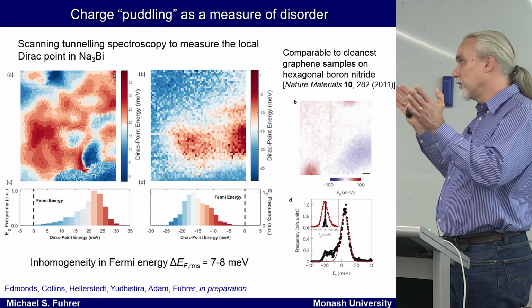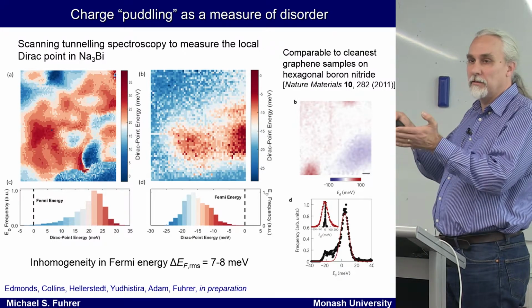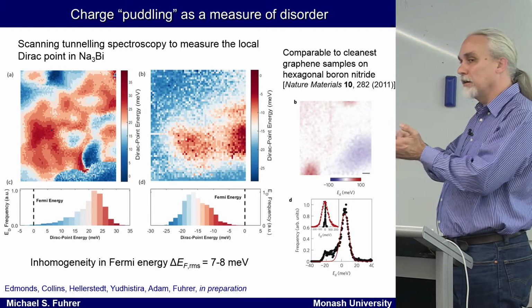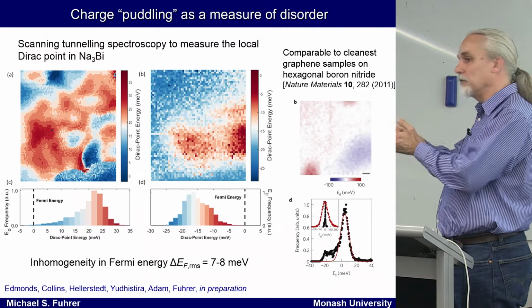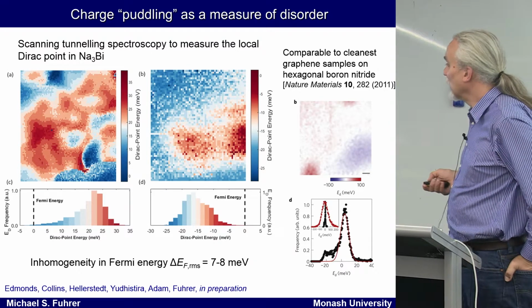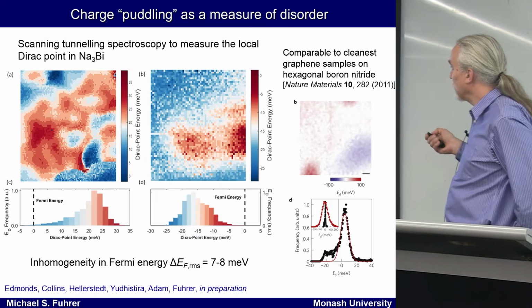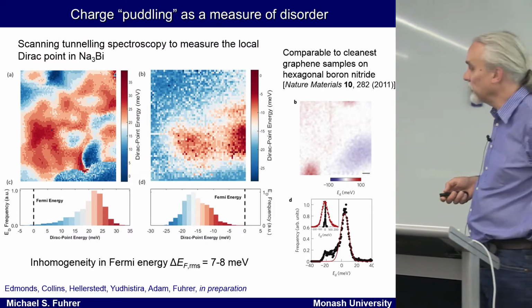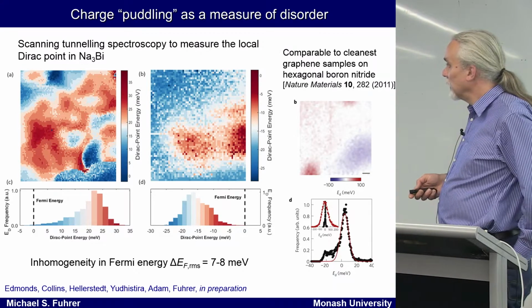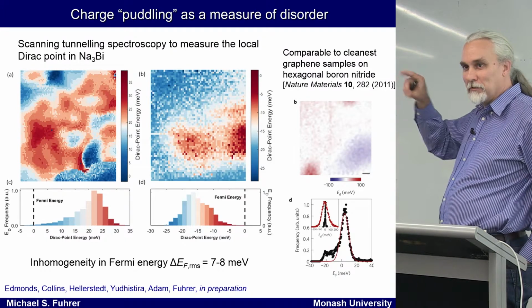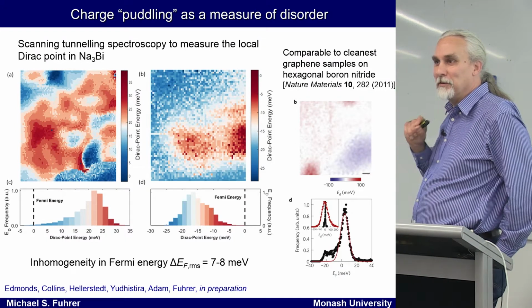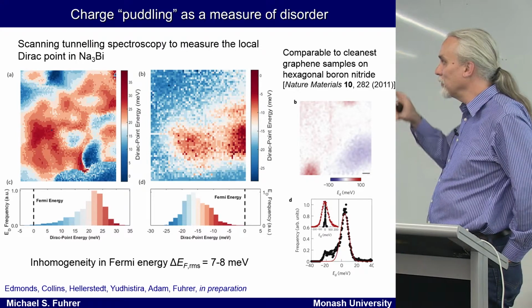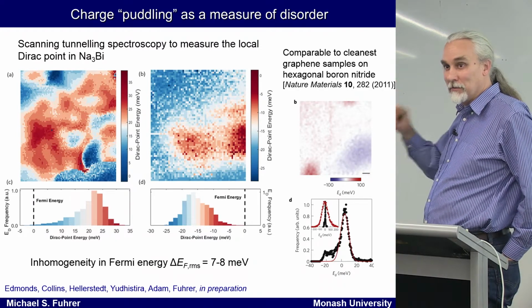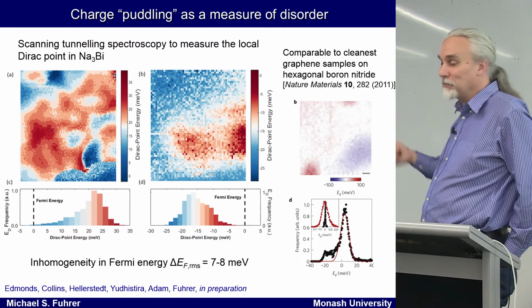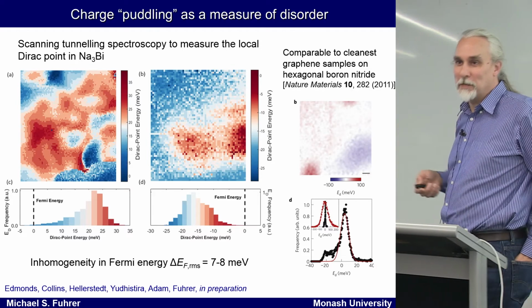So it tells you sort of how close you can really realize this Dirac-like band structure, how close you can get to the point of that cone. And it's comparable to the very best graphene samples. So that looks really good as well. So what we're trying to do is make these very thin films to see this transition to a conventional insulator, and then apply an electric field and see a transition to a topological insulator.